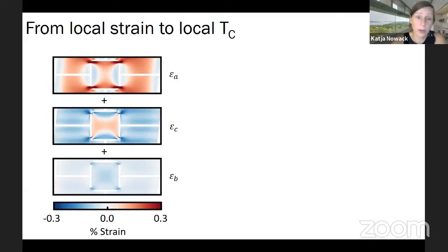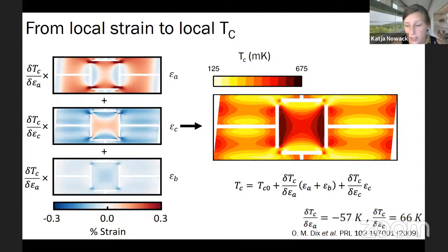We can do a more careful job and use finite element simulations, which we've done in COMSOL to simulate what the strain field will look like. Here you see simulated strain maps, three strain components, for the first device that we measured. Now we can take the information from the hydrostatic pressure measurements and figure out how much Tc should shift per unit strain applied along the A-axis and the C-axis. From the strain maps, we can then predict a local Tc map for the device. And this is what is shown here.